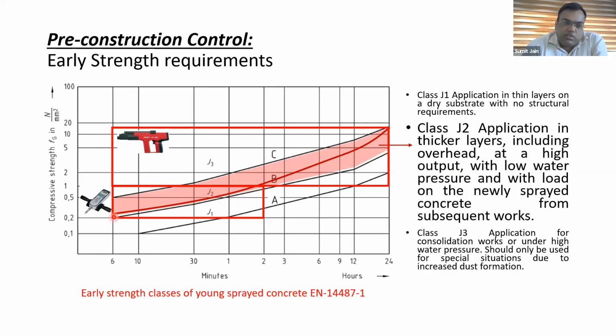So this is a plot of the compressive strength versus time, in minutes and hours. For the initial period up to 2 hours, or say less than 1 MPa, we are using a penetrometer, and for more than 1 MPa, we are using the Hilti shotgun method to test these early strength requirements. And mostly the shotcrete strength should start very near to the J2 curve, and by the end of 1 day, or say 24 hours, it should actually reach right up to J3. So this is somewhere around 12.5 MPa or 13 MPa maybe, and within 1 hour it should have 0.5 MPa strength.